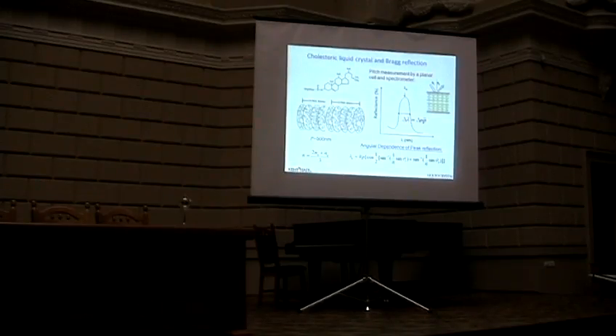Okay, so here is the Bragg reflection. If you put them into a cell with the helical axis perpendicular to the substrate, at the no applied voltage condition, 0 volts, this helix is supposed to form a very perfect alignment. Then you will have some issue of angular dependence, which means that at oblique angles you see a different helical pitch, as a cosine theta effect. So the wider the angle you have, the shorter the pitch. That's the angular dependence that everybody knows on this cholesteric material.